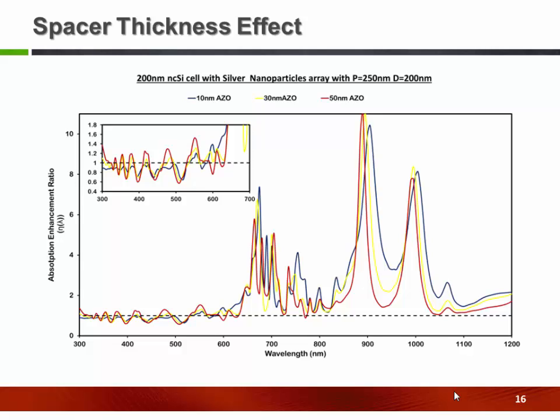The other thing is the spacer, or the distance between these metallic structures and the absorbing layer. As I have investigated, generally by increasing the distance of these metallic structures from the absorbing layer, the performance decreases. That mainly depends on the mechanism of the improvement, which is related to the coupling of the incoming light to the different waveguide modes, which I will explain later. And normally we have a limitation on the distance. We could see that if we are close enough to the absorber layer, we could get a very good result.